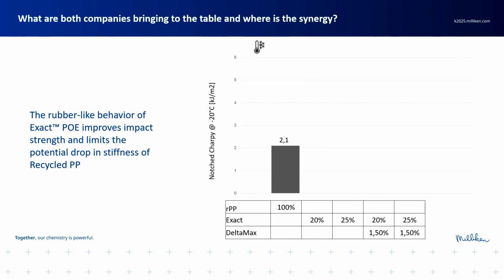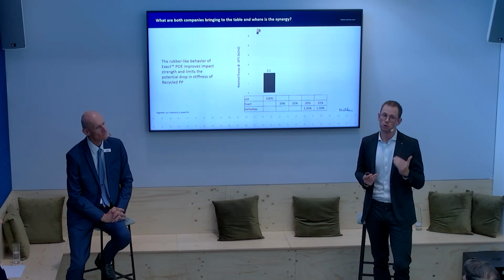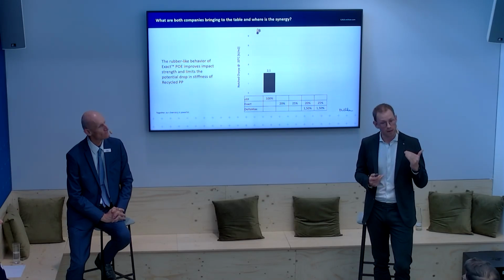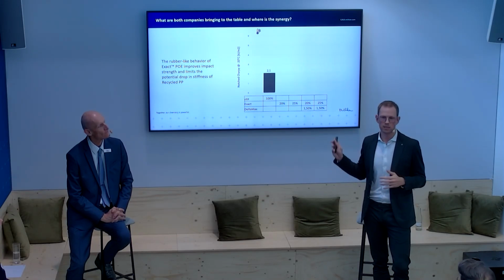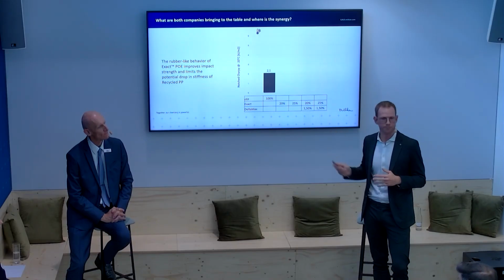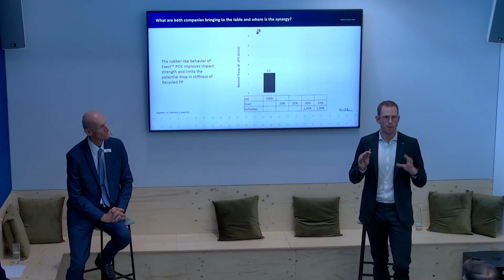In this case, we measured at minus 20 degrees. Depending on the automotive part, you need to go lower. If you talk about bumpers, you probably need to go lower, to minus 30, minus 35, to meet the requirements. But in this case, we have picked minus 20, just to keep it a little bit more general.